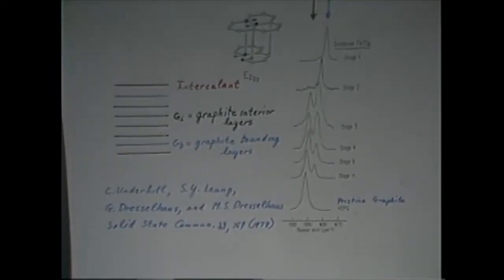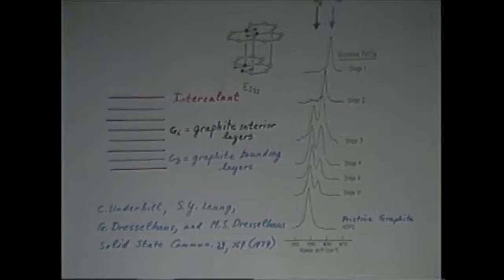And the first thing that we looked at after the magnetoreflection was the phonon modes. Phonon modes are significantly different from electron modes. So if we see nothing in the electrons, maybe we should see something in the phonons. So this seemed like a totally unrelated experiment. Let's see if we see anything in this case that tells us that we've intercalated.